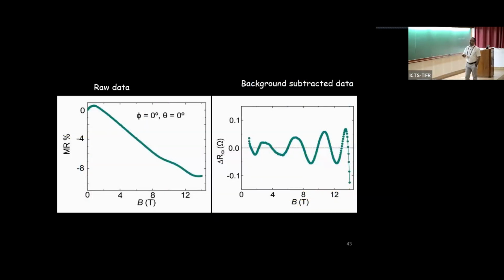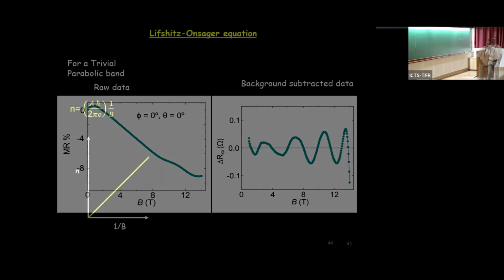So this is the raw data of our quantum oscillation as a function of magnetic field. This is the magnetoresistance. When you subtract this background, you can see this kind of oscillation, which is not as good as what people see in semiconductor material, but for an oxide material, believe me, it's not a very bad oscillation. There is something called